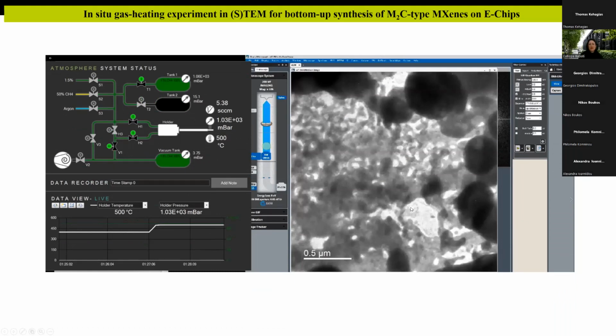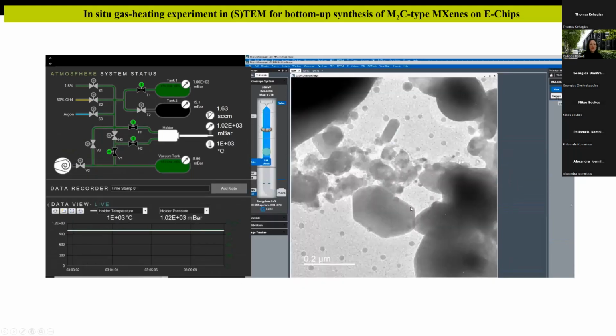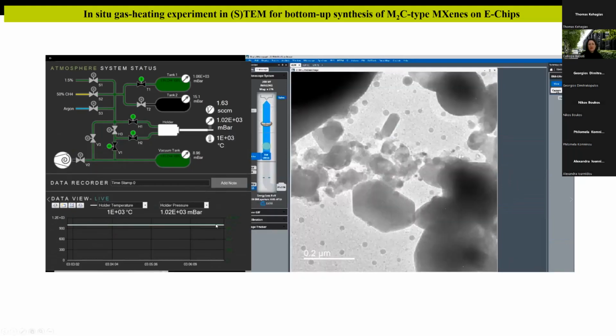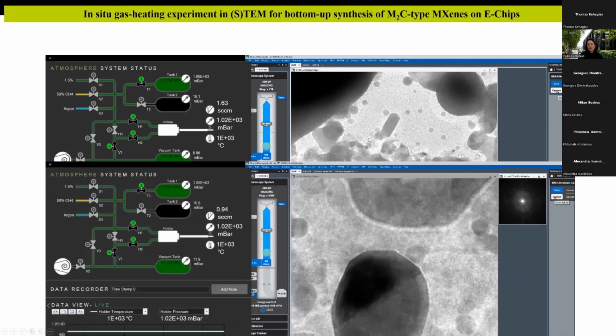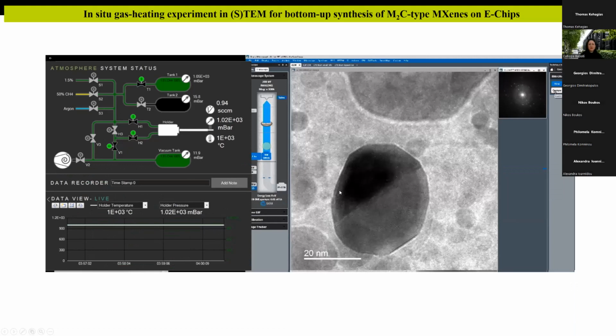So you can see that gradually we have changes. And then we reached the regime, the values that are suggested by the CVD process. So we reached the highest temperature and the highest pressure of methane. And you can see that we started having this nice formation of flakes. Some of them were micro-sized, and also we had nano-sized flakes.